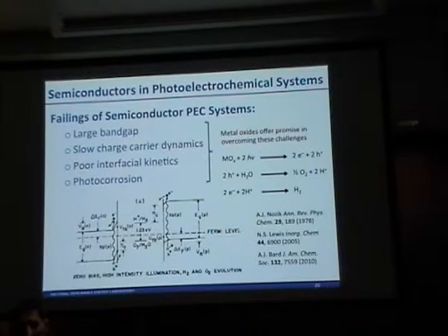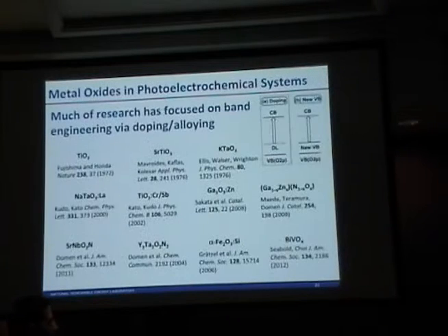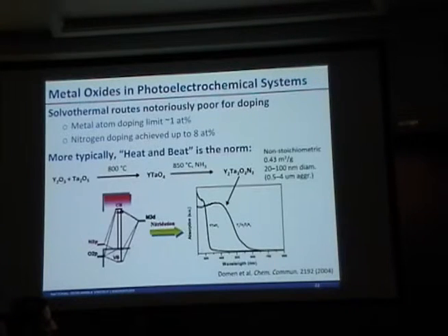So typical catalysts will require 300, 400, 500 millivolts of overpotential, and those are some of the best catalysts known. On the hydrogen side, your conduction band needs to be above that of the hydrogen production potential. And so there are energy constraints that basically will pin the conduction band to a certain level. Pushing it down significantly oftentimes will put it below the level of the hydrogen reduction.